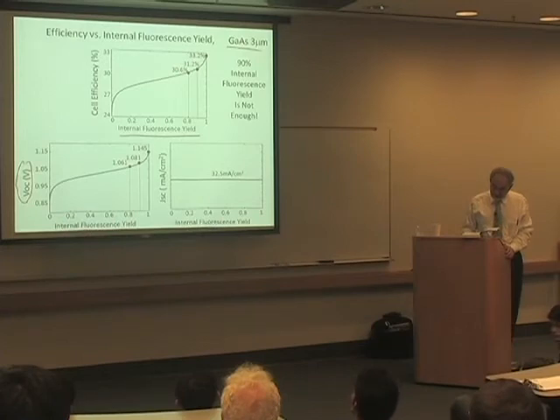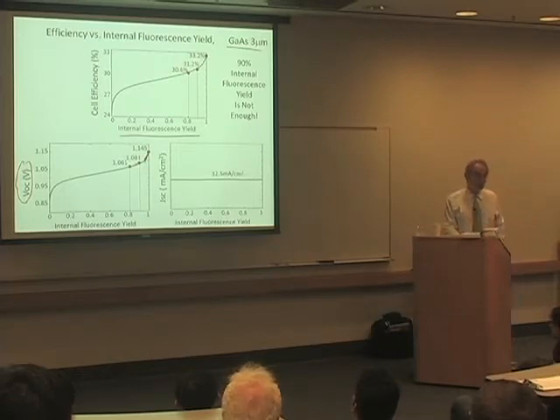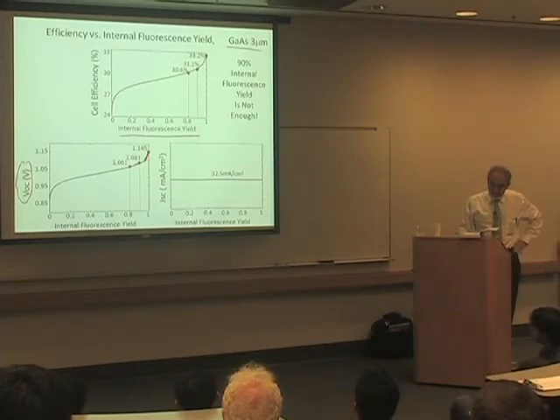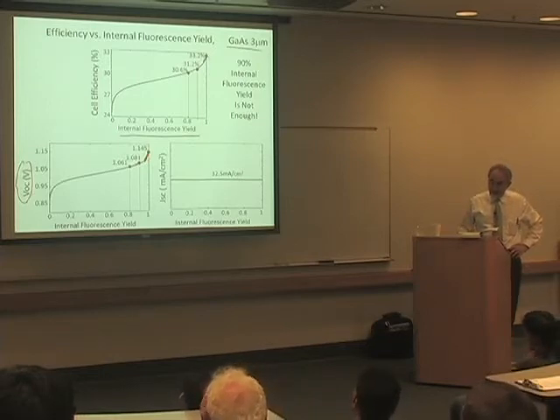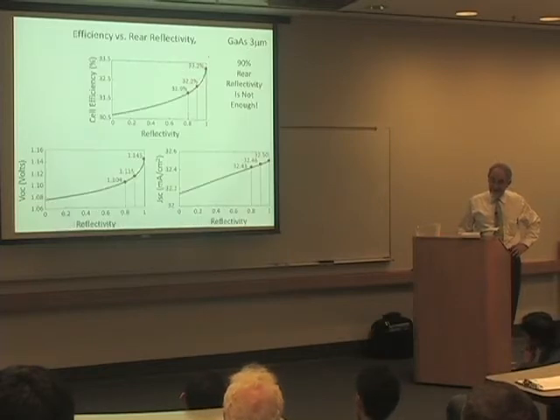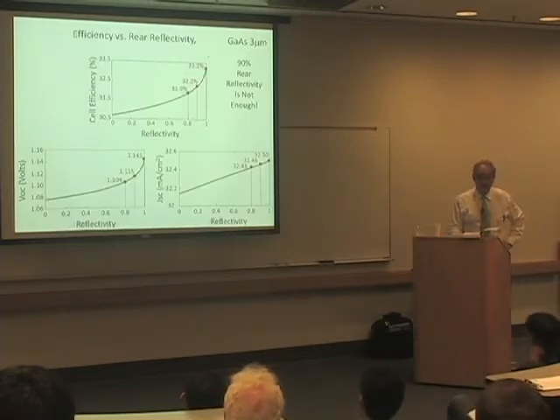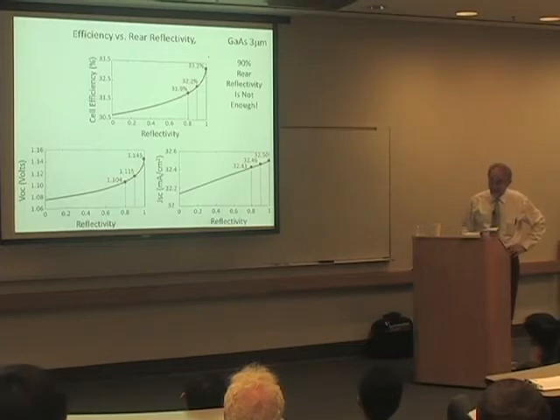Yes, you help yourself by making the internal fluorescence yield bigger, but the most help is that last little bit as you go from 95 to 99%. So you have a tremendous improvement. 90% is really not enough. And likewise, a tremendous improvement of efficiency just as you approach 99 and 100% internal fluorescence yield. Same thing with the rear reflector. Very important to have a rear reflector. 90% is simply not enough.